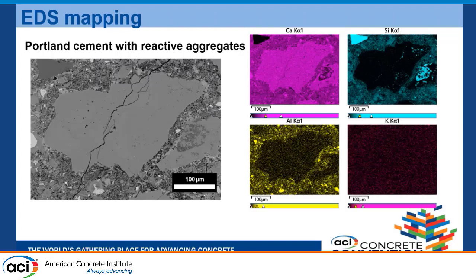It is visible in the image, and the silica on the right is visible because we use Spratt siliceous limestone, so we expect to have silica there. And aluminum, because the cement has aluminum, so we see some traces of that. But the most interesting thing would be to see traces of sodium or potassium. Here it's uniformly distributed.